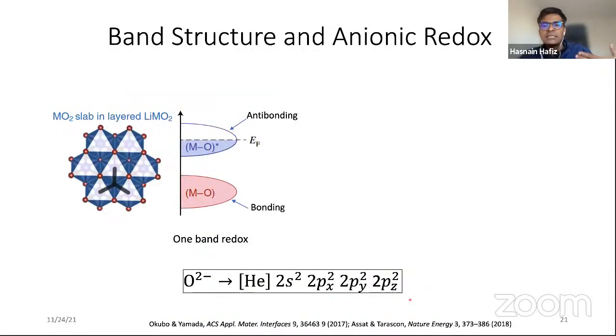Now we consider the Lewis configuration of oxygen electronic structure, which shows one 2s and three 2p doublets, where this 2s stays deep in energy and becomes redox inactive. Only these 2p orbitals are involved in the redox process, and these high energy 2p orbital doublets participate in metal and oxygen bond formation, where their involvement depends on the local structure of the material.